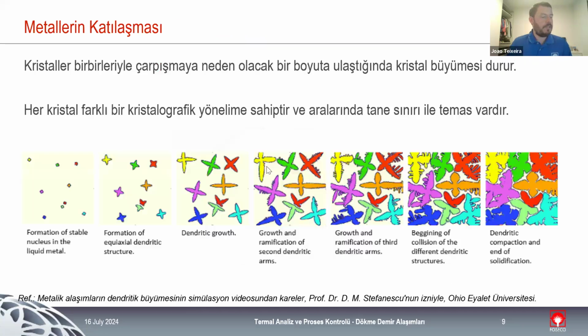And nucleation happens after that. So we have random spots inside the liquid metal with stable nuclei. The stable nuclei start to grow, to get bigger as time goes on, as solidification happens. They start to grow, they start to get bigger, they start to go against one another. And at the end, we have what I showed in the first picture. We have grain boundaries and we have a lot of stable nuclei growth inside the liquid metal.